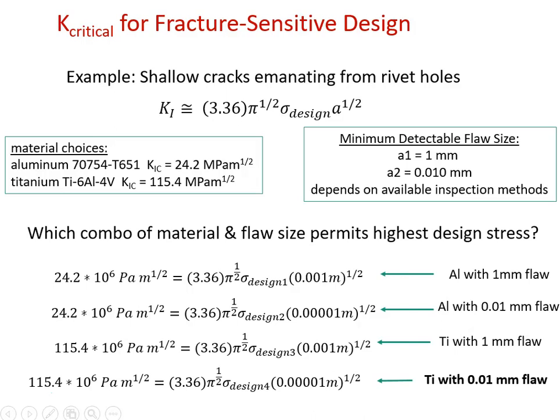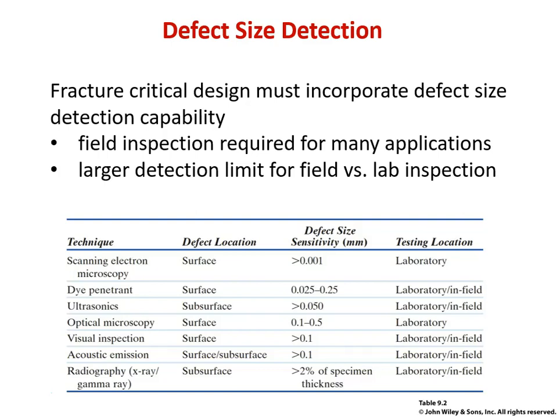But quite often flaw size is more difficult to detect since it is processing dependent, whereas K1C is material dependent, and if you have test data, you can know what that is for sure. So just a word on defect size detection, since this is as important as your K1C, effectively in determining how much load you can apply to a material before it fractures.